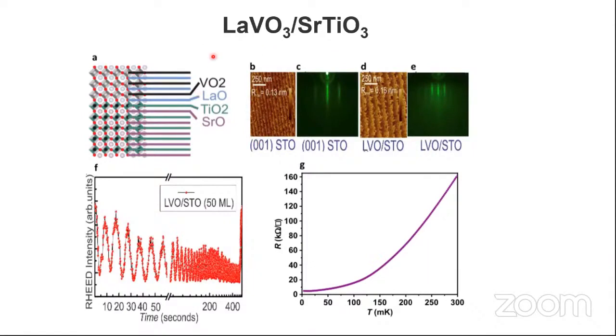Before depositing LVO by pulsed laser deposition, they prepared the substrates of STO. These are titanium oxide terminated STO substrates. And this is the AFM image after growth of LVO on STO. And these are the RHEED patterns. If we count the number of peaks, then we know that 50 monolayers of LVO were grown on STO. And the interface became conducting. This is the resistance versus temperature. This shows that we have a metallic interface at the junction between LVO and STO.